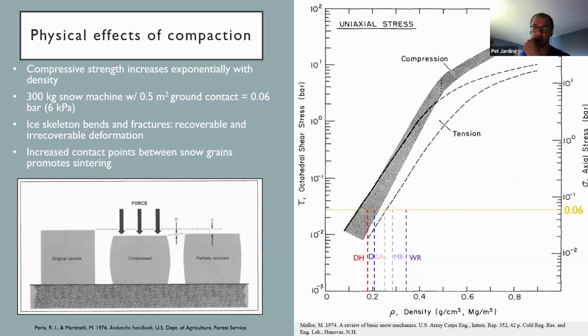per cubic centimeter. Depth hoar falls comfortably under this, which explains why it was the most reduced by compaction, while dendritic snow is on the fringe. And just to be clear, this is the failure point of the snow. So if it's above this point, it will still increase in density and hardness. But this is when you put it under pressure and it gets smushed. This is the weight where that happens.